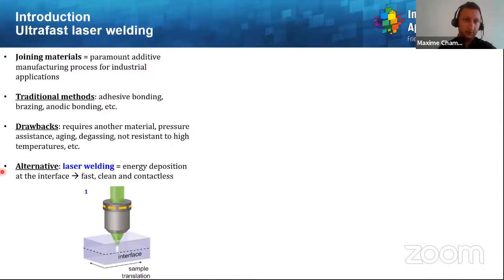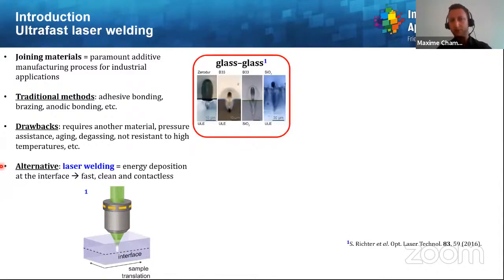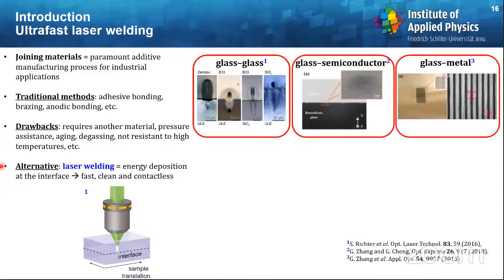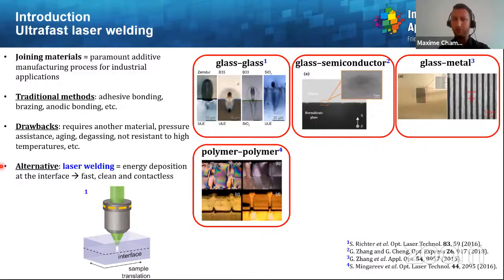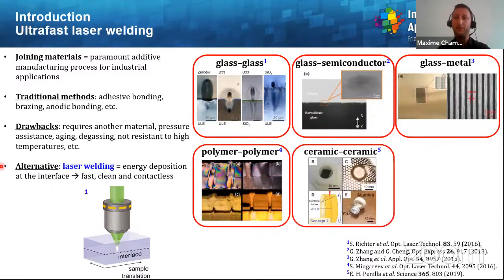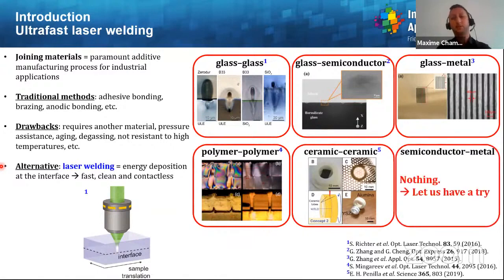Then an alternative was developed to solve this problem, which is called laser welding, which consists of energy deposition at the interface between two materials, as illustrated here. And this provides a fast, clean, and contactless way to join those two materials. This was shown to be applicable in many material configurations, such as glass to glass, glass to semiconductor, glass to metal, polymer to polymer, and more recently, ceramic to ceramic. However, in the semiconductor to metal configuration, there is nothing too convincing so far. So let us have a try.